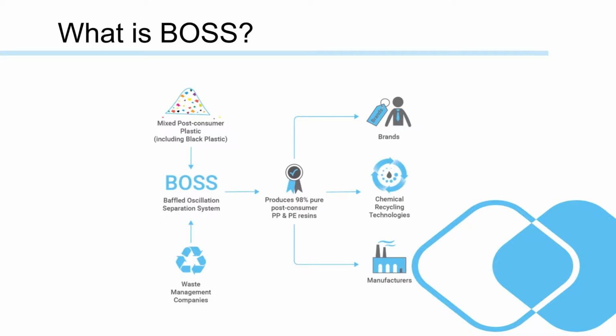We put it through our shred and wash process to first prepare the material for the BOSS technology, then putting it into BOSS to recover in excess of 98% pure post-consumer PP and PE resins. The yield that we get is about 70%. What we have coming in is a gate fee item, which we typically take in for free. And we end up with a regrind, which we sell back into UK manufacturing for values in excess of £500 per tonne. Our customers are a range of brands, including the likes of Unilever.